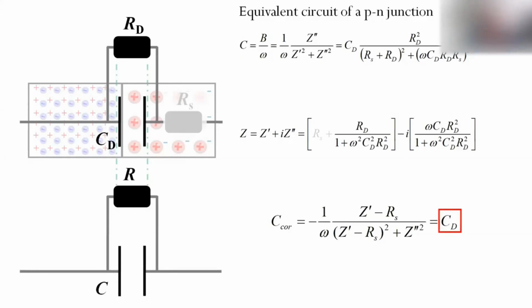So this is one feature of impedance spectroscopy. We do this correction in our research for series resistance and for parasitic inductance, and then we use the corrected parameters to calculate the concentration of free charge carriers, which is a very important integral parameter in organic photovoltaic devices and in any devices, because the concentration of charge carriers will define the net rate of recombination losses.